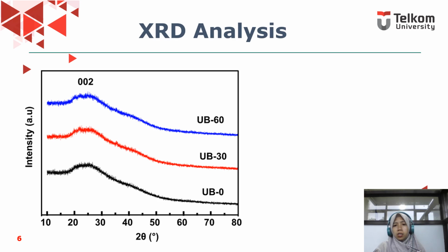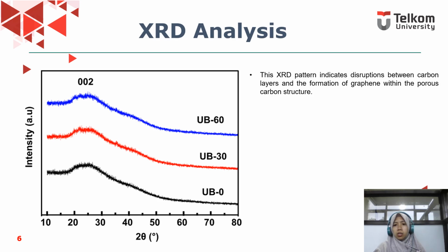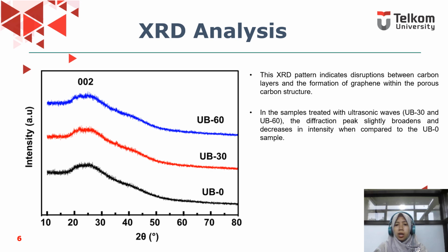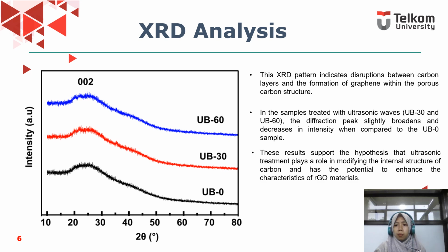The XRD analysis. This XRD pattern indicate a disruption between carbon layers and the formation of graphene within the porous carbon structure. In the sample treated with ultrasonic waves, UB-30 and UB-60, the diffraction peak slightly broadens and decreases in intensity when compared to the UB-0 sample. This result supports the hypothesis that ultrasonic treatment plays a role in modifying the internal structure of carbon and has the potential to enhance the characteristic of RGO materials.